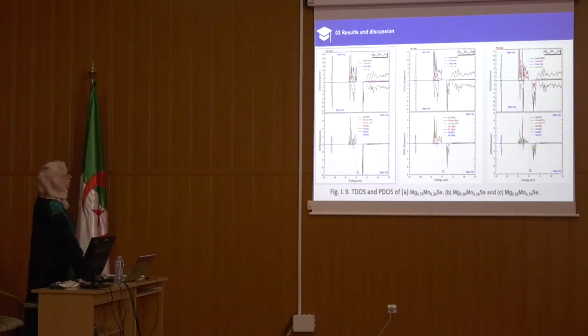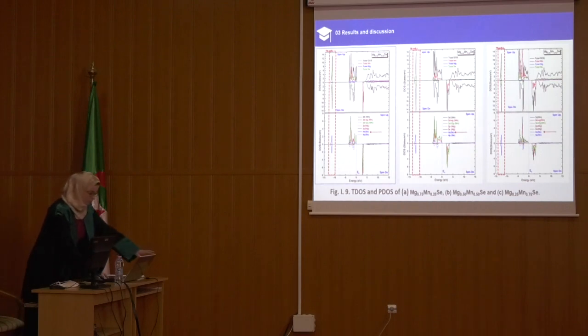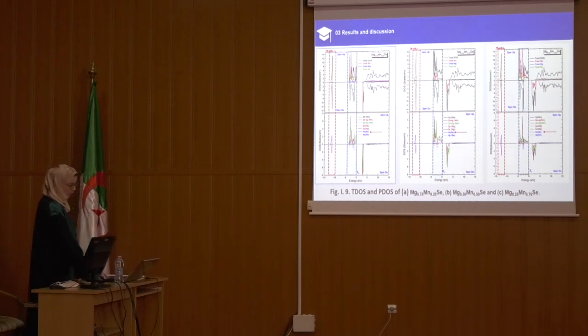Here we present the total and partial density of states for each element. For the first range, between -12 and -11, it is formed by 4s orbitals of Se atoms for both spin up and down orientations. In the middle part, around -5 to near the Fermi level, the density of states comes essentially from the hybridization between 3d Eg and 3d T2g manganese states and 4p Se and 3s Mg states in the spin up case.